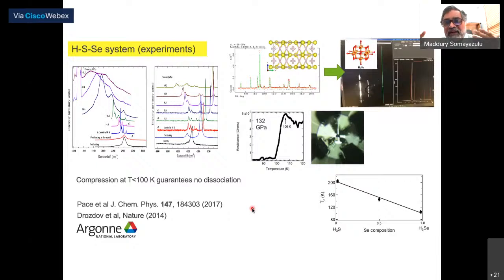Why? Well, the question we're trying to address is, how does the central atom contribute towards the transition temperature? And what is its contribution in this whole system? Okay, so it turns out that you can actually mix sulfur and selenium and modify the stoichiometry, and it's a very continuous curve. You can change sulfur and selenium as much as you like, and you can form a solid solution. And from the Raman spectroscopy, we know that the selenium is going to the same site as sulfur, and it's tuning the interactions appropriately. You can actually see a sulfur-hydrogen, selenium-hydrogen vibration, and the effect it would have on the hydrogen vibron. Again, a lot of detail I'm not going into, but just giving you an idea.